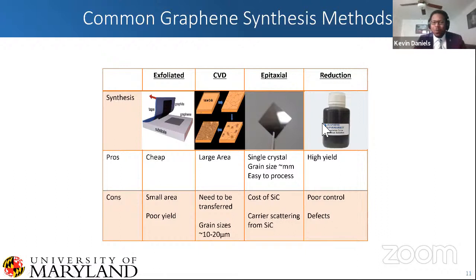So all of this points towards this epitaxial route, which basically uses silicon carbide, which really has been the backbone, I would say, of a lot of advances in power electronics. But you can actually grow graphene using that material, which can now go up to 6-inch wafers, and you can get single crystal grain sizes greater than 1 millimeter. Very easy for processing, because you're building on a substrate that's for the most part CMOS compatible. But the issue is the cost of silicon carbide, which again, is going down dramatically. And you also have carrier scattering from silicon carbide, because of the electron phonon coupling that I'll show in the next slide, to contend with on the material.